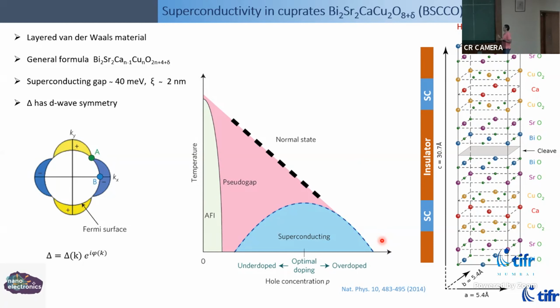Within a couple of hours, if you have a very thin layer, this material degrades very rapidly. So you have to take exceptional measures to make devices very quickly and cool them down to below 200 Kelvin. Once it's below 200 Kelvin, the mobility of oxygen diffusing out of the layers is very slow or stopped completely. Then you can measure devices for months at a stretch with no problem. But at room temperature, the oxygen becomes off-stoichiometric very quickly, and you have to work hard while making devices, as I'll point out as we go along.